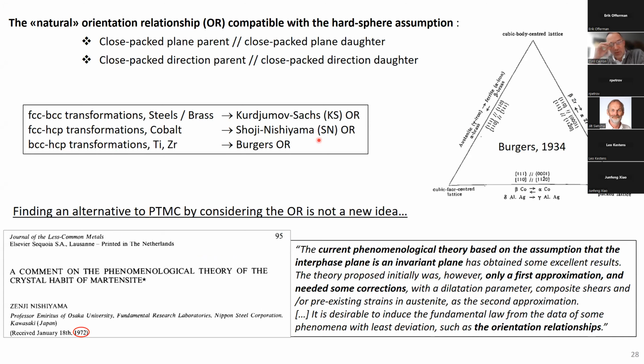If I want to do calculations, I need anyway something. I need to assume a specific orientation relationship between the parent phase and the daughter phase. But in that case, what is natural to me, I would say, is to assume that in this orientation relationship, the close-packed plane of the parent phase is parallel to the close-packed plane of the daughter phase, and the close-packed directions of the parent and daughter phase are also parallel. And this is the case in many phase transformations in metallurgy.